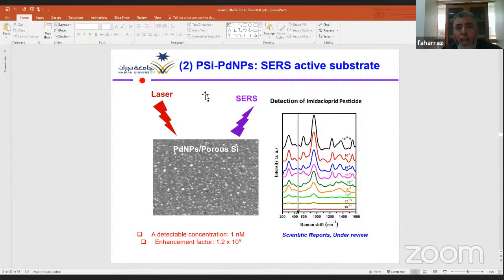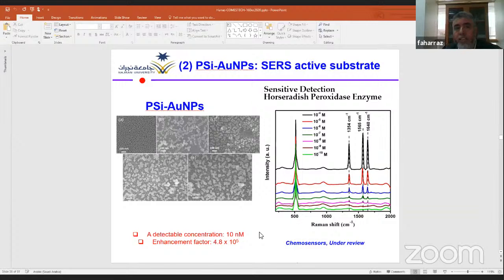It is under review, and it is the utilization of porous silicon decorated with palladium nanoparticles to detect a pesticide, imidacloprid, with a detectable concentration of 1 nanomolar and an enhancement factor in the range of 10^5 times. And the last example of a SERS active substrate is the fabrication of gold nanoparticle-modified mesoporous silicon substrate, and we have successfully used this substrate for the sensitive detection of horseradish peroxidase enzyme, and this work has been submitted and is under review in Chemosensors.